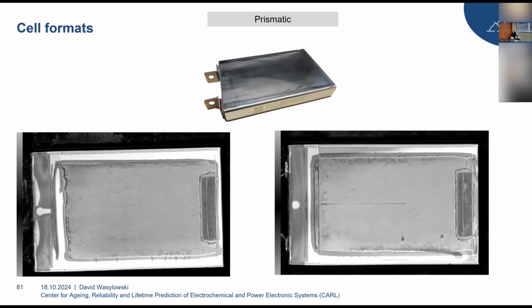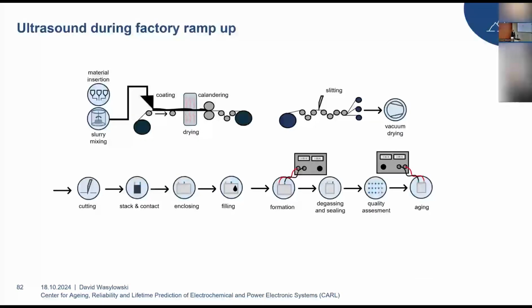But by accident, we found one cell which had this line indication here and those two holes. And we further assumed by an ex situ analysis that this line defect and these two holes are actually mechanical defects in the electrodes during coating. So this motivated us to try and introduce this ultrasound imaging technique in the manufacturing process of lithium-ion cells that you can see here. And the image that we just generated could, for example, be used in an end-of-line testing after all of the manufacturing processes have been performed, to not build such a defect cell in a battery pack, which then might cause problems during operation.